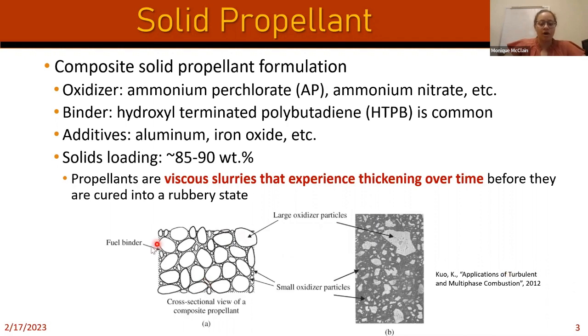So typically the particles will be an oxidizer. Some of them will look like large particles like this. You'll have some coarse particles, you'll have some fine particles in between to help improve our packing ratio, but we'll have oxidizer, which tends to be ammonium perchlorate in the propellant. That makes the majority of the particles, and they tend to look like crystals. Essentially, they look a lot like sugar. And then we can include some other particulate additives. For example, we could include some aluminum particles to help it burn faster, or we could include iron oxide as a catalyst. And there are plenty of other additives you could include in your mixture.